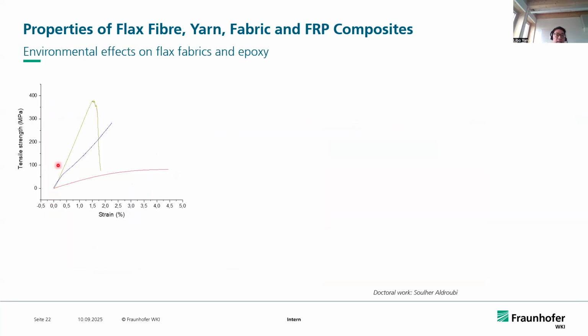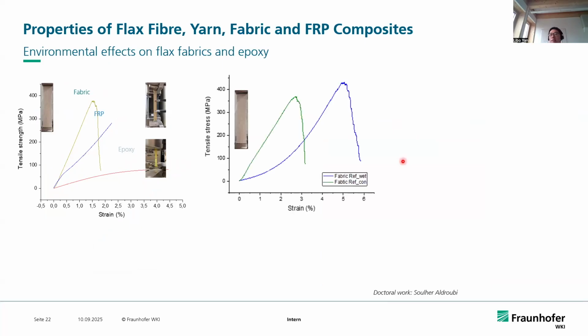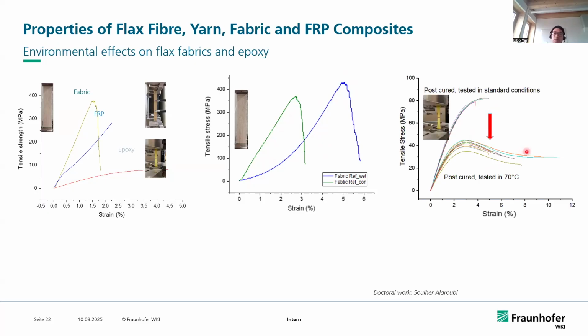In this figure, you can see the tensile stress and strain curves of the epoxy, the flax fabric, and the flax fabric reinforced epoxy composites. But what I want to say is the sensitivity of the flax fiber and the epoxy to different environmental conditions. In this figure, you can see the flax fabric tested in tension at the dry condition. The blue line is the flax fabric after 24 hours of exposure to water and tested in the wet condition. There was a significant reduction in the Young's modulus, and a slight increase in the tensile strength of the fabrics.